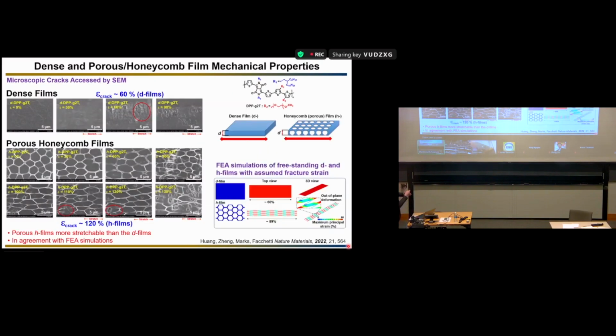Another advantage of this web architecture: these are the dense film and this is the honeycomb film. Here we transfer the film onto an elastomer and start stretching. Here I stretch in this direction. For the dense film, it starts cracking at about 60% strain, whereas for the honeycomb, it starts cracking at about 110, 120.